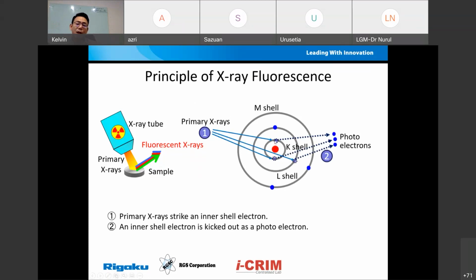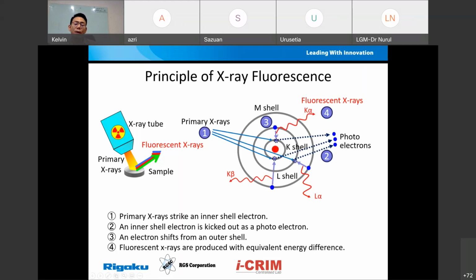Imagine when the electron is kicked out from the K shell, an electron from the L shell automatically tends to drop into the lower shell. By doing so, it needs to give up certain energy. This energy given up is what we call fluorescence. When an electron drops from the L shell to the K shell, it is considered K alpha, and from the M shell to the K shell it is K beta. So what is very important in WDXRF, what we always talk about, is K alpha, K beta, L alpha, and different types of lines.